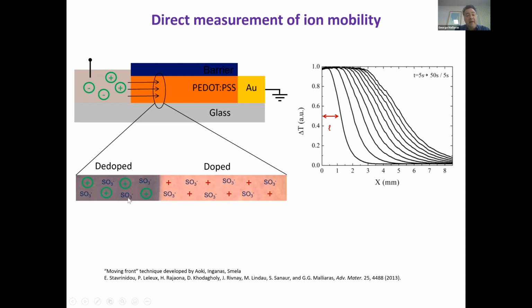So as you do that, you have PEDOT, which is normally doped. It has the fixed sulfonate ions, and then the holes that can move about. And when you inject cations under the influence of an electric field that is applied laterally between the electrolyte and an electrode, then these ions will compensate the sulfonate anions, and holes will be extracted through the gold. So as you do this experiment, you apply a potential, you start injecting cations, they start compensating the anionic charge, holes get extracted, this bit of material gets de-doped, and you have this de-doping front that moves inside the sample.